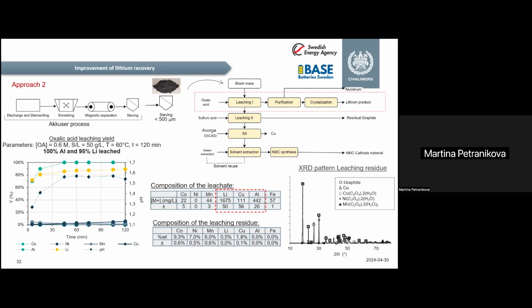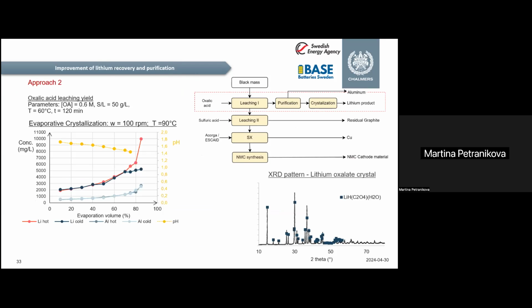But what was also very interesting in this approach was that with this experimental design, she also recovered 100% of aluminum. So in one step, we could recover all the lithium and also all the aluminum, which is the impurity in the system. So then we could skip one step for the removal of the impurity. And as I said, it was mostly lithium and then also aluminum, and then the rest stayed in the solid residue. So it was also very simple to then separate the solution from the solid residue.